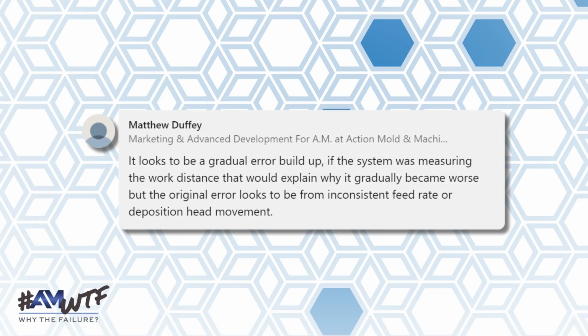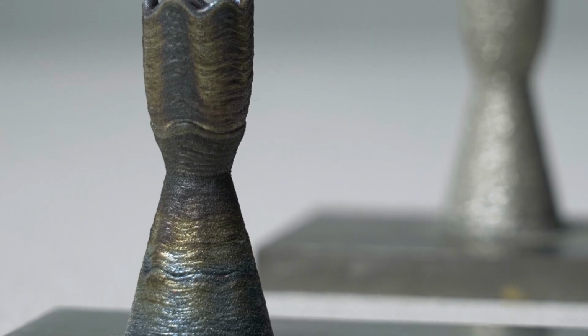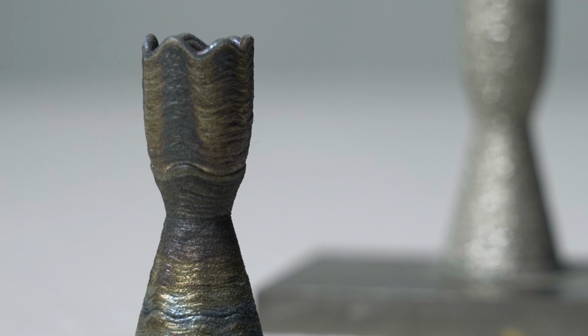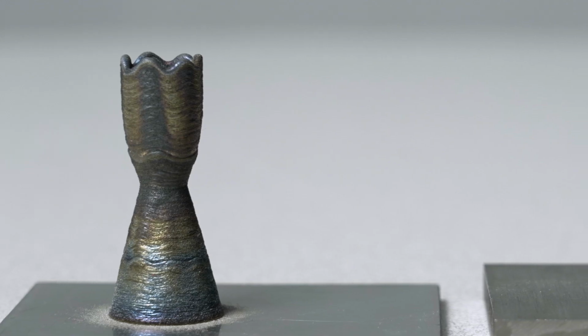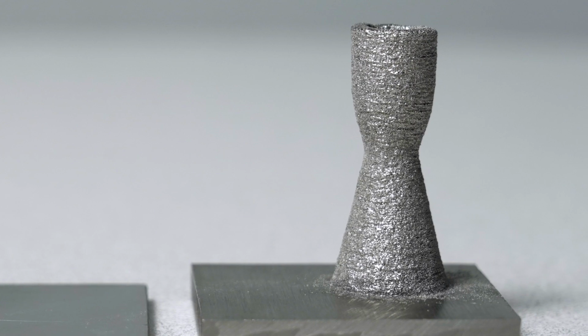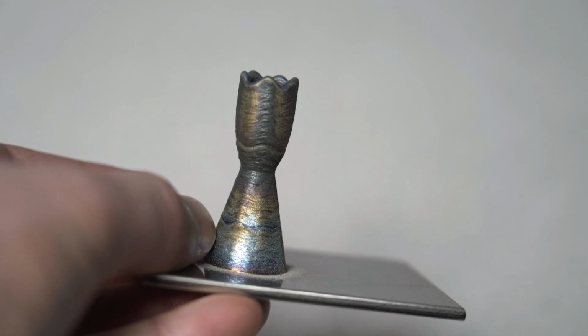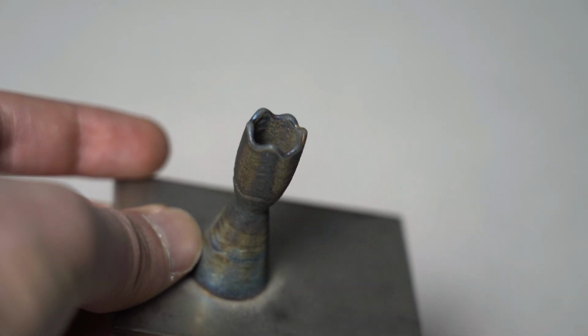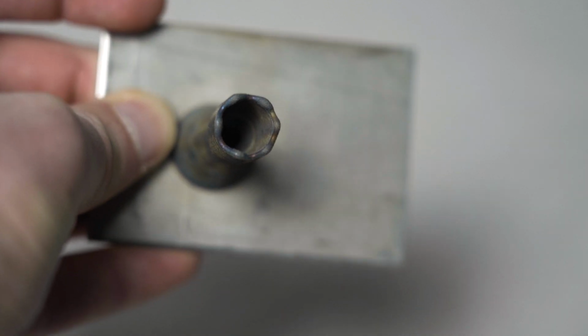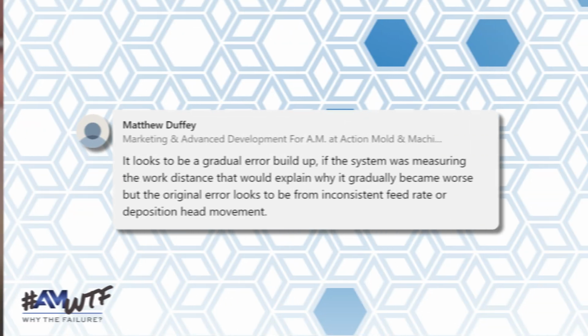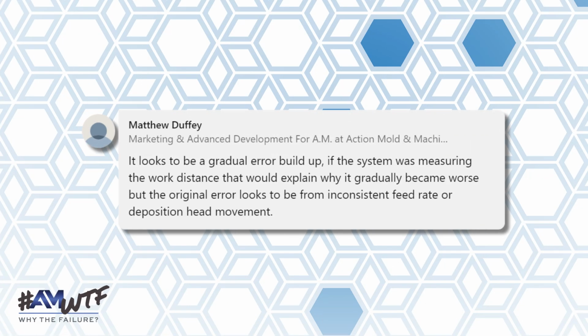Absolutely. I think you captured it really well in the picture there. The nice close-up that Matthew noted as well is that this is a progressive buildup. If you look side by side, you can see on the failed one that waviness, which ends up looking like the parapets on a castle on your rook piece. It starts building right at about that neck, that narrowing area, and as it goes up, it gets progressively worse and worse until eventually that top layer is created. So the error there comes back to perhaps an inconsistent feed rate, the deposition head movement getting progressively worse over time.